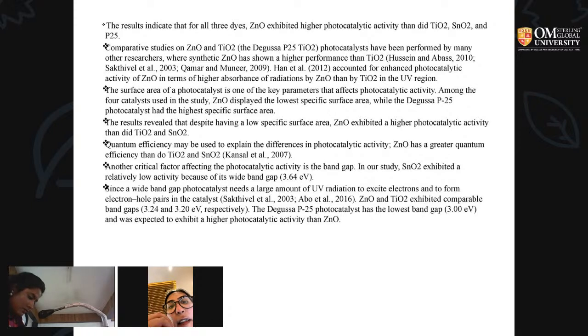Also, a critical factor affecting the photocatalytic activity is the band gap. In our study, tin dioxide exhibited a relatively low activity because of its wide band gap, that is 3.64 electron volt, since a wide band gap photocatalyst needs a large amount of UV radiation to excite electrons and form electron-hole pairs in the catalyst, while zinc oxide and titanium dioxide exhibited comparable band gaps, that is 3.24 and 3.20 electron volt respectively. Next slide.